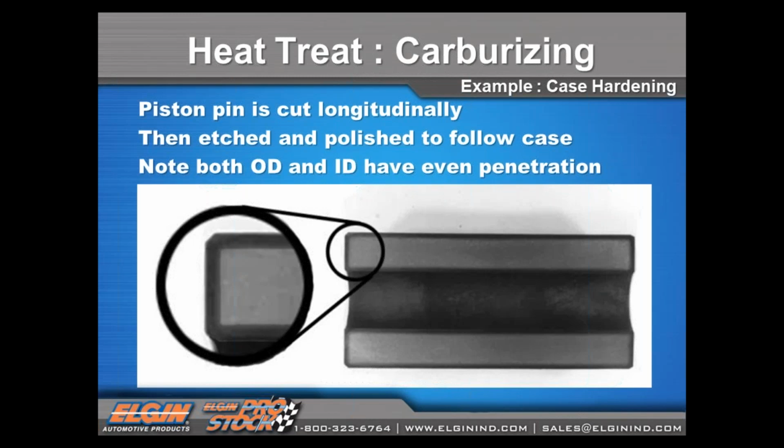So this picture is just a cross section, a longitudinal section through a piston pin a little bit bigger than an automotive size. This is probably a diesel piston pin at a smaller, like an 8-9 liter range. So this is cut in half lengthwise, and then it's polished down and etched with nitric acid and alcohol to reveal the case. And you see the case goes on all surfaces that are exposed to the carburizing